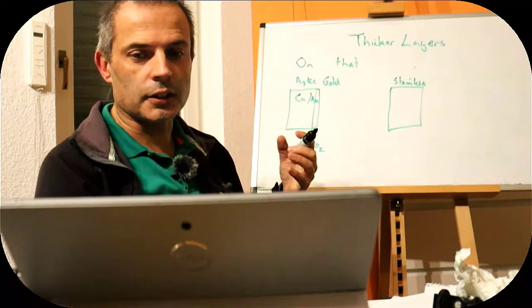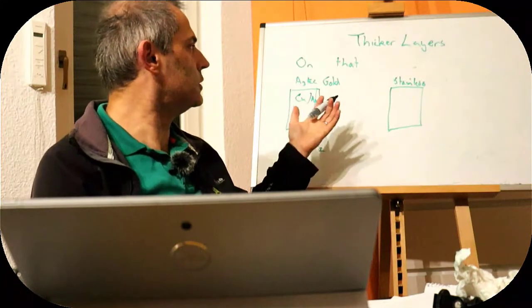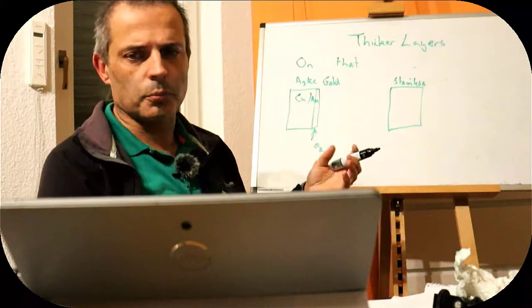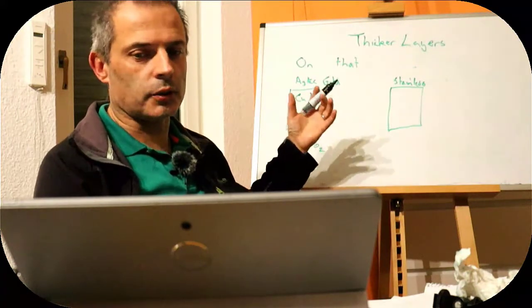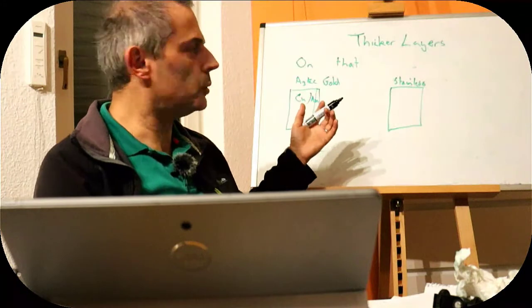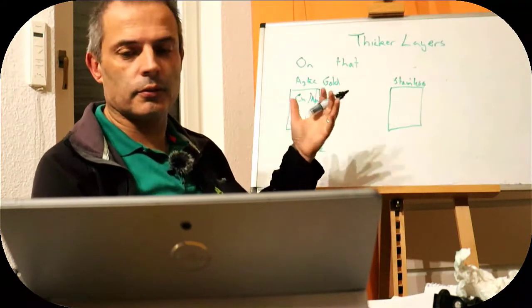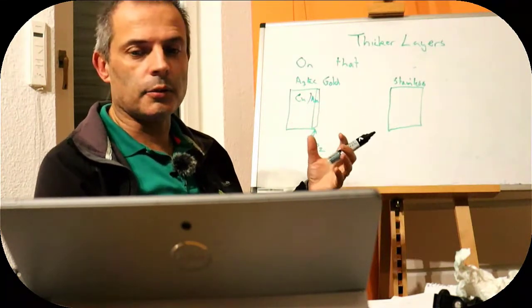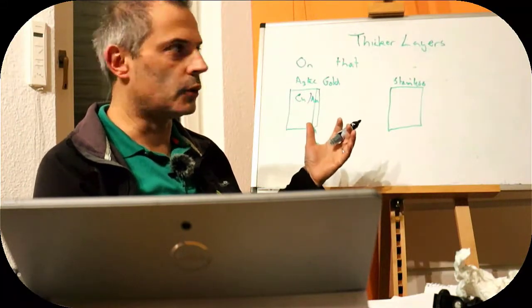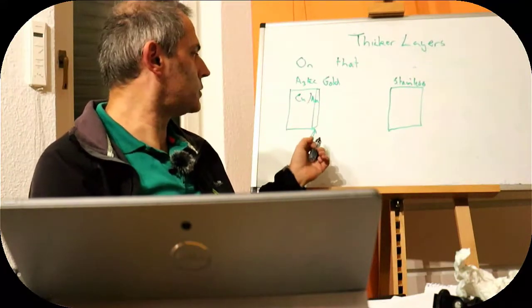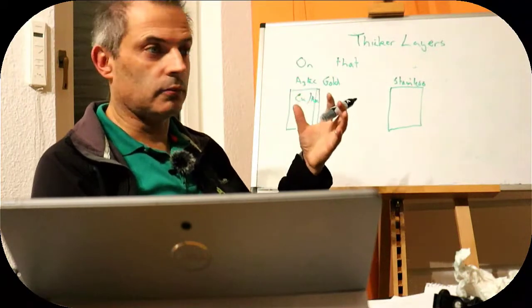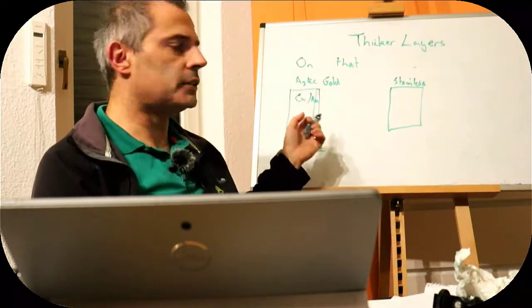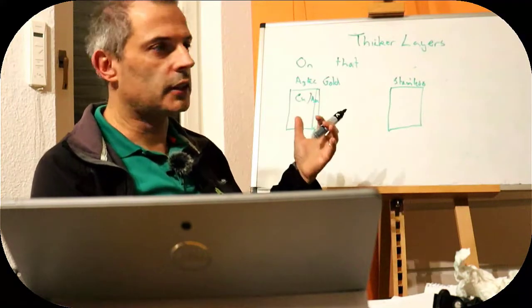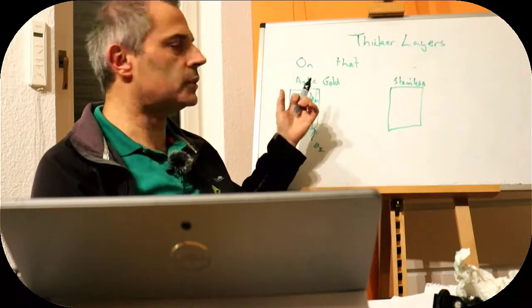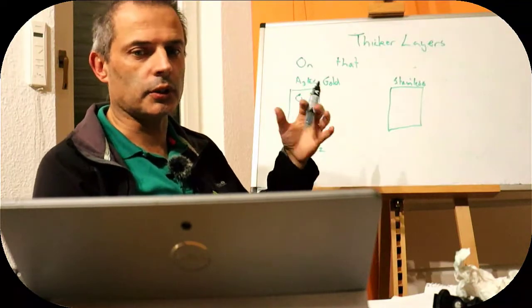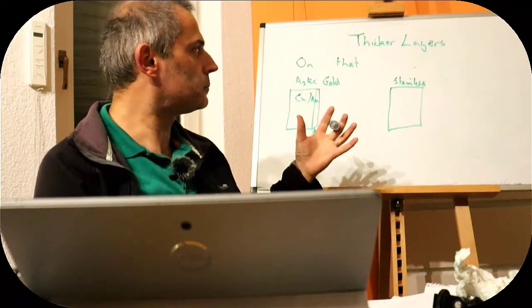Then the Aztecs used to post-treat it by dipping it into hydrochloric acid, or possibly other acids, but hydrochloric acid is one of the ones that I've heard mentioned. That will take off the oxide layer and leave the part looking like it's pretty much gold. It won't look like pure gold because it's mostly copper, but it will look a lot more like gold than the base metal. For the Aztecs that was important because for their religious purposes it had to look like gold and not actually be gold. That was their religious purpose.